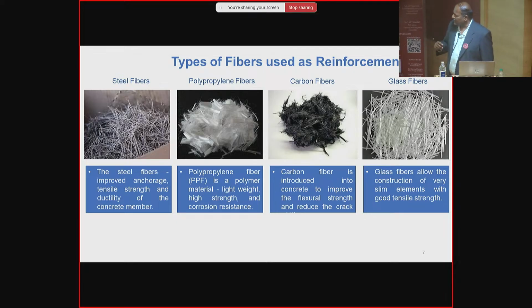And the polypropylene fiber is used in concrete where the fire resistance is to be increased, mainly for high-rise buildings, for grades of concrete above M80, M90 and all. The higher the grade, the lesser the fire resistance. So if you want to increase the fire resistance, you have to use these polypropylene fibers at around 0.1 kg per meter cube, so that during a fire, these fibers will melt at 160 degrees, and it gives ways for releasing the pore water pressure developed inside the concrete, right?